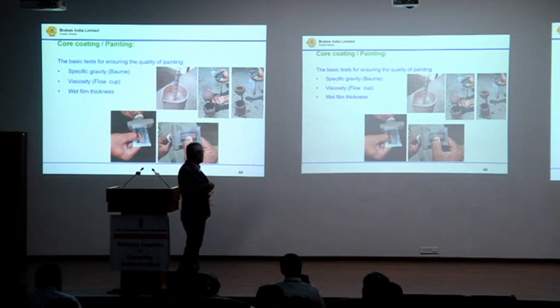The basic tests carried out for core paint during the process: specific gravity with Baumé, viscosity with flow cup, and wet film thickness with gauge.